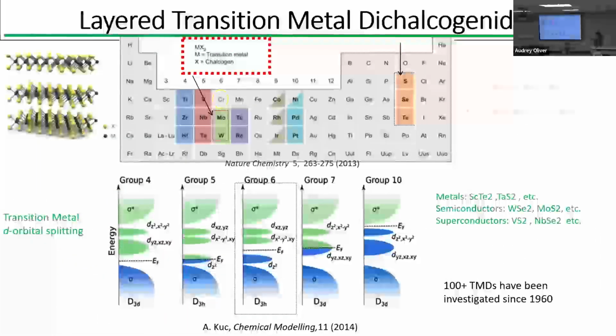Okay, so let's look into structure and properties. These are layered materials. In plane they have strong covalent bonds, and out of plane is weak van der Waals, right? So if you just take into account the covalent bonding, using standard DFT like LDA or GGA to calculate properties, this interlayer distance would be large, right? It's not taking that binding into account. That's why we need to use a van der Waals functional, and we can get an accurate structure.